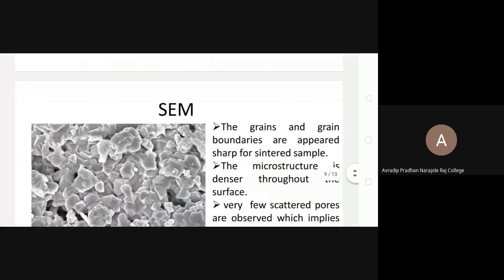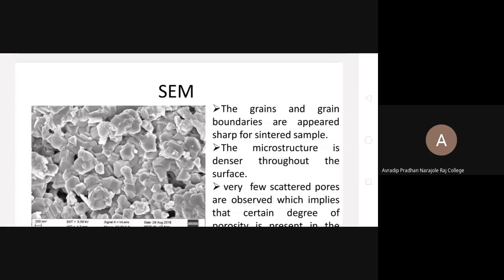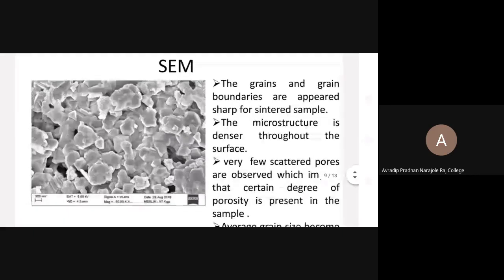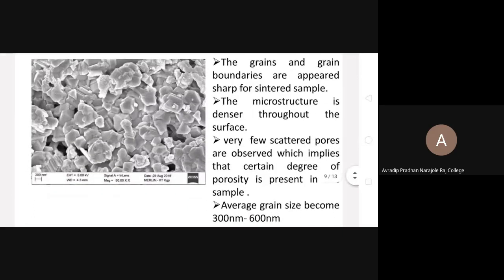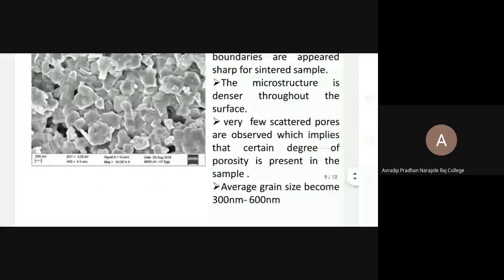The next slide is the scanning electron microscope, from which we have seen a very clear picture, and the grains and grain boundaries appear very sharp. For the sintered sample, the microstructure is denser throughout the surface, and a few scattered pores are also observed. We have calculated the average grain size to be 300 nanometers to 600 nanometers.